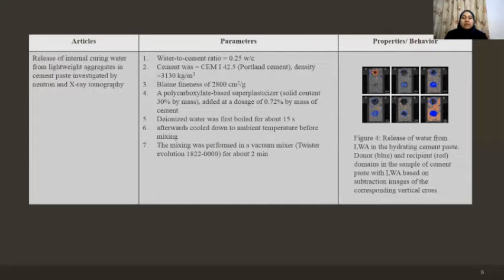A polycarboxylate-based superplasticizer, with solid content 30% by mass, was added at a dosage of 0.72% by mass of cement. The deionized water was first boiled for about 15 seconds. Afterwards, it was cooled down to ambient temperature before mixing. The mixing was performed in a vacuum mixer for about 2 minutes.